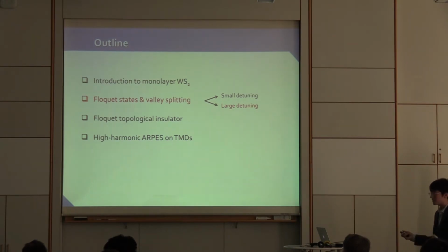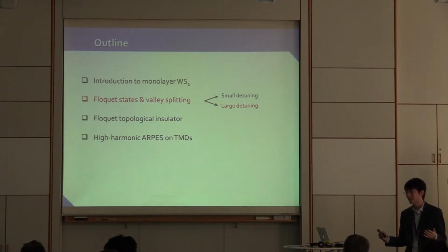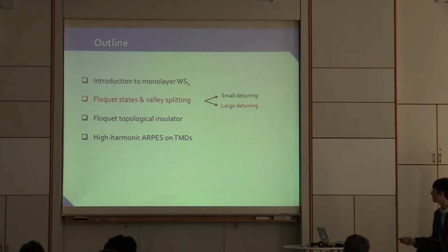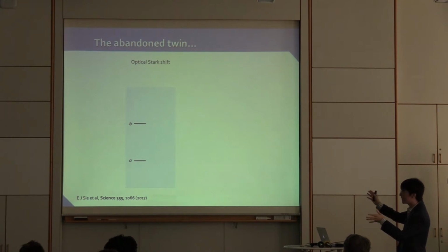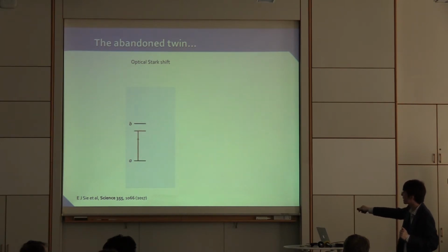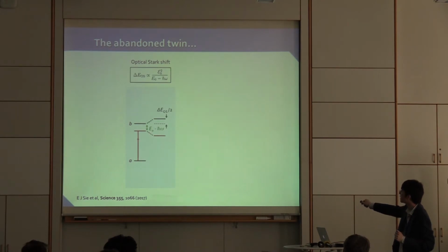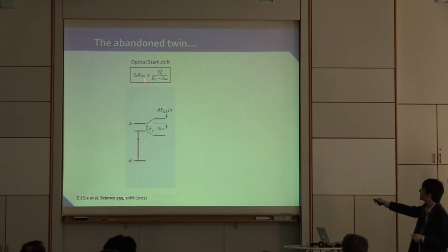So this is interesting because one of the things that it will show is that something breaks down, the Jaynes-Cummings model breakdown and so on. But okay, we have been discussing the Floquet states, the shifting of the energy levels through the optical Stark effect, and this is what happens, right? Ground state A, excited state B, we pump with light below the gap, and it will have this energy difference between the photon energy and the gap, and this will increase the gap by this amount, E naught squared over E g minus h bar omega.